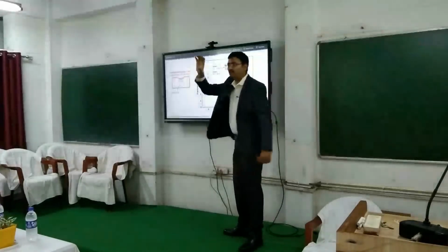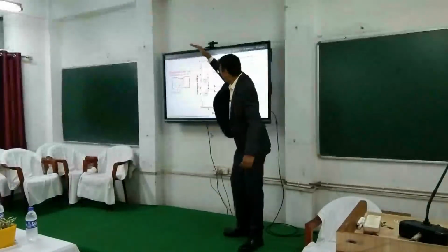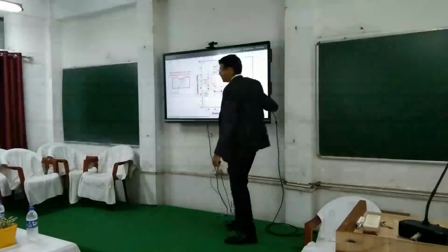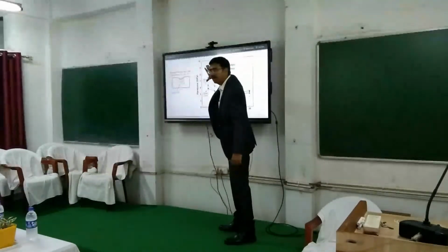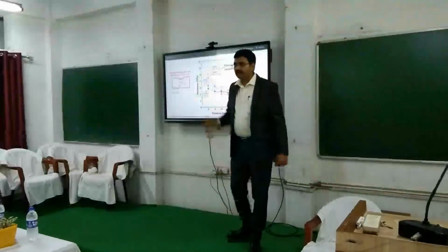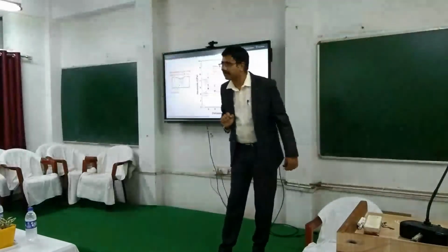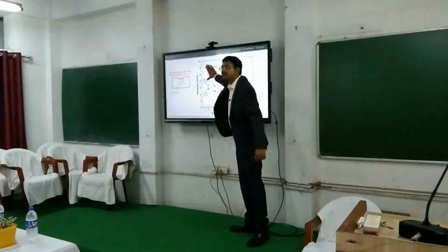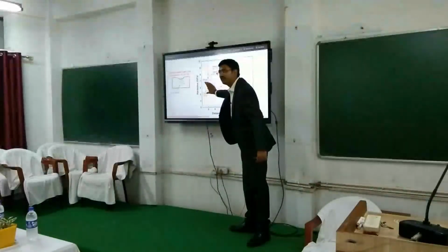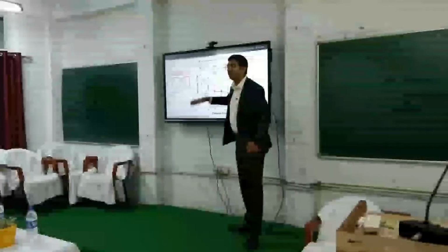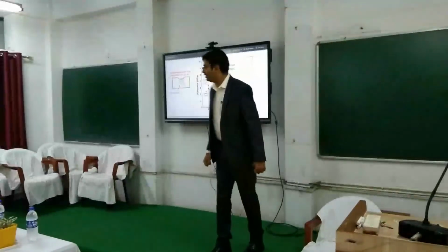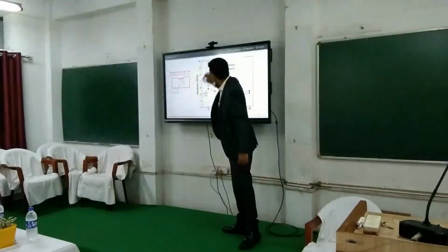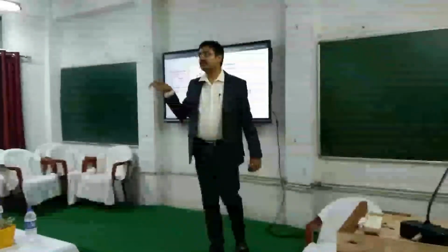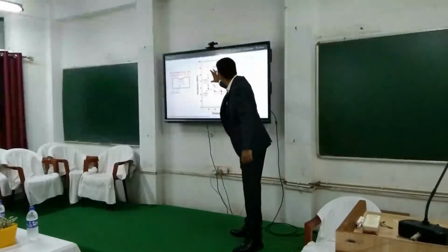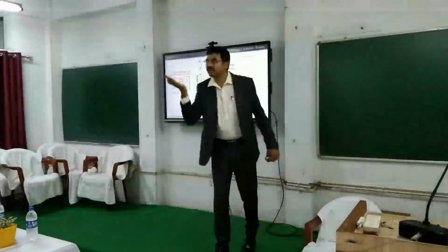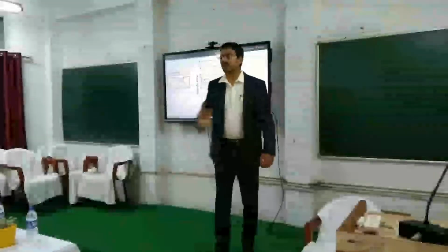This 0 corresponds to the top surface where you have the tribolayer, and this way we are going away from the surface. Okay, so initially at the near surface, the hardness of tribolayers where they are formed, since you have small carbide particles embedded inside these tribolayers, you see the near surface hardness is very high compared to titanium 64 where the hardness is low. Okay, the error bars are big because these tribolayers are very heterogeneous in nature. So that's why we are seeing big error bars. But if you look at the average, average hardness of the near surface of composites due to tribolayer formation is higher. So if the near surface is higher, it has more load bearing capacity and lower wear rates.